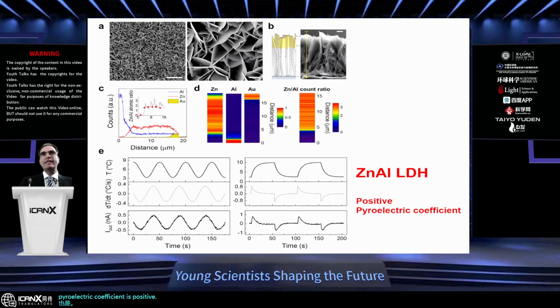The pyroelectric coefficient is also positive. Then, as another example, it is also very interesting to see that we measure the composition as a function of height, and as you see, there is a lot of aluminum at the bottom because it's close to the aluminum substrate, and when we go up high, we find less aluminum and more zinc because, of course, of the growth of the nanoplatelets. So there is a significant composition gradient that is also expected to improve the pyroelectric coefficient.